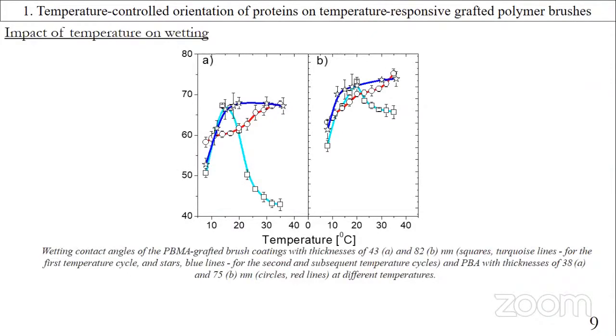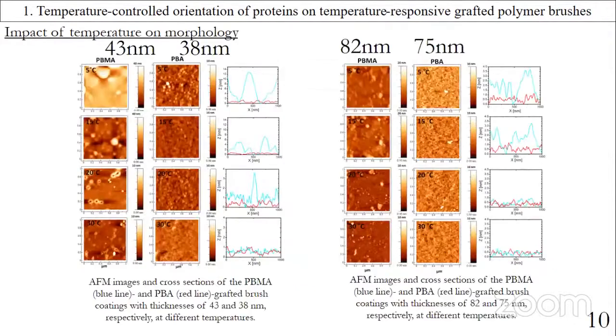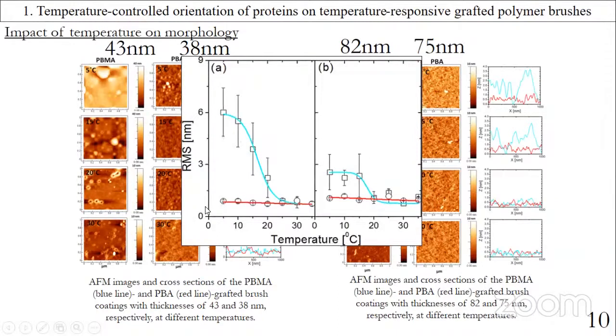The contact angles were measured for PBMA grafted brush coatings with thicknesses of 43 and 82 nanometers, as well as for PBA with thicknesses of 38 and 75. The AFM data from the PBMA grafted brush coatings suggest the transformation of the surface morphology from very rough and structured to relatively smooth at an increased temperature. For PBA coatings, no morphological changes at different temperatures were observed. And the RMS values estimated confirm a morphological transformation for the PBMA coatings.